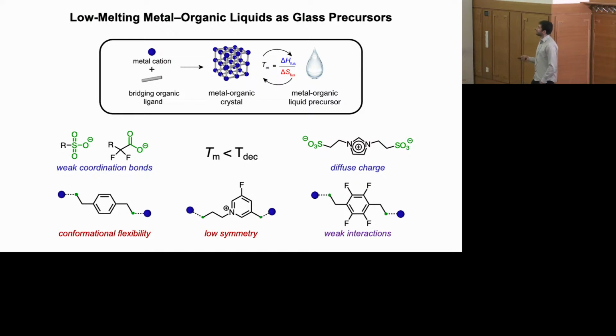And so in particular, we were interested in trying to develop ways of bringing the melting temperature of these extended materials below the thermal decomposition temperature. And so we developed a number of thermodynamic strategies for thinking about how to do this, including trying to really weaken the interactions between bridging organic ligands and the metal cations of our materials, trying to incorporate additional conformational flexibility into our bridging organic ligands to have very low symmetry organic ligands that would provide an increased entropic driving force for conversion from the crystalline solid to the disordered liquid.